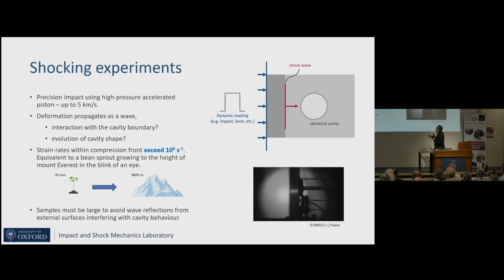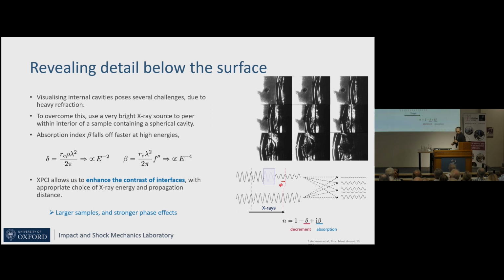Okay. And the other thing just to say is that if we want to do this experiment, what we really want to isolate is this initial shock wave as it interacts with the cavity. We would rather that shock wave not bounce around and rattle around and interfere with the very pure type of loading that we're producing. So we've got a massive sample. So what do we do? Well, unfortunately, because it's a large extended volume of material and cavities are by definition inside something, we find it very difficult to peer into the materials, especially if they're opaque.